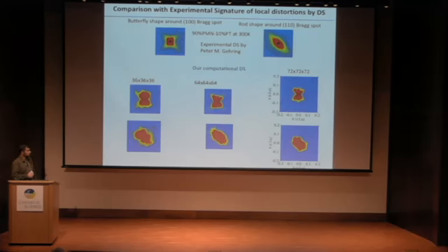Okay, so now we can look at the diffuse scattering, which is a very well-known technique for studying these kinds of relaxor materials, and we can compare the diffuse scattering that we get to the diffuse scattering that is experimentally observed, to validate our calculations and also to perhaps explain the origin of diffuse scattering. So here is data by Peter Gehring, this is for 90% PMN-10% PT composition, and we have this butterfly shape around 100 and a rod shape around 110.